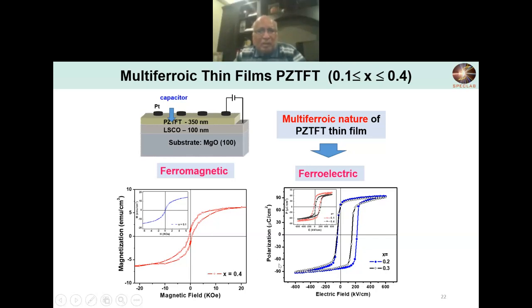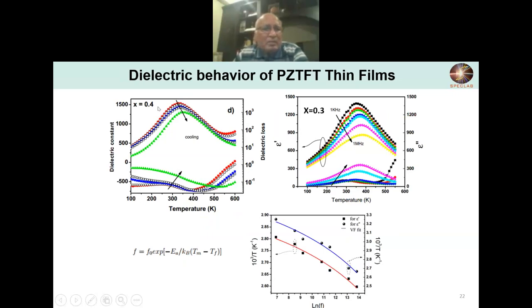And the dielectric values were also very good. Here plotted is 0.4. 0.4 becomes a little more relaxed. It will relax a little bit, because you can see that there's a shift in the maximum as a function of frequency. So this is an indication of some kind of relaxation occurring in thin films for x equal to 0.4. But the most ideal one is 0.3 here. There is practically no relaxation of any kind, and you have x equal to 0.3 with good data and very nice dielectric constant, and losses were low. You can see the losses are very low.